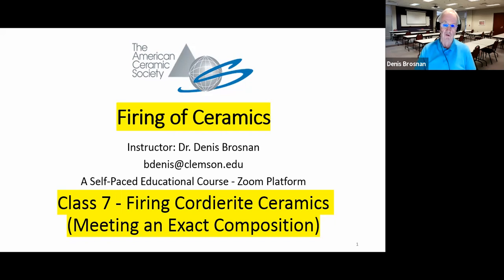Further, the silica itself at the firing temperatures for these products is converted at least in part to cristobalite. And then we have, on cooling, the inversions of cristobalite and maybe quartz as well to deal with to avoid cracking, or it's called dunting, in those types of products. So firing porcelain is more difficult than firing the earthenware ceramics.